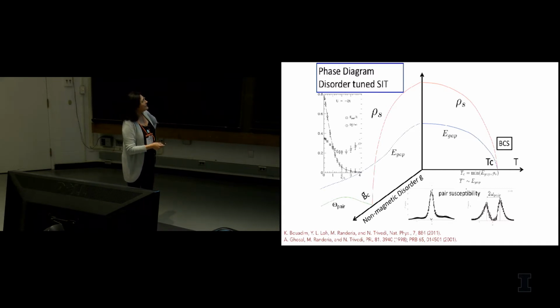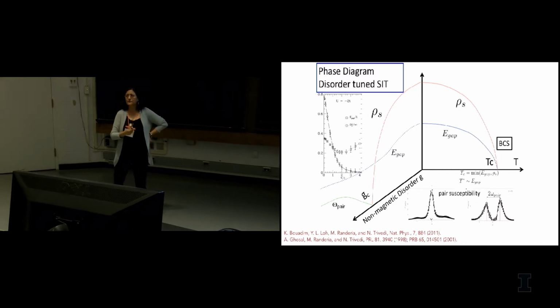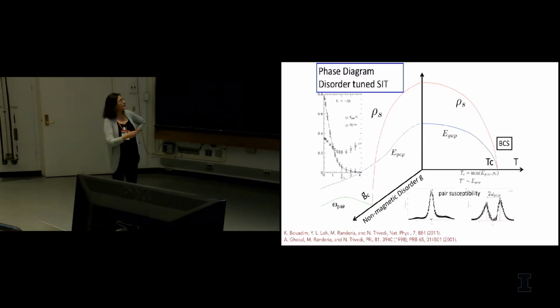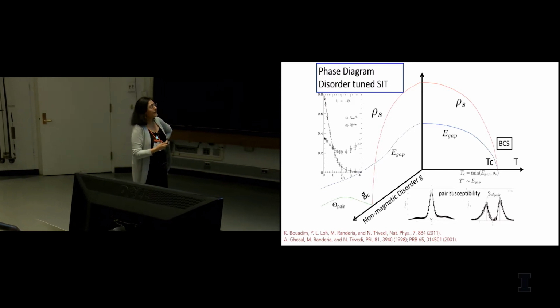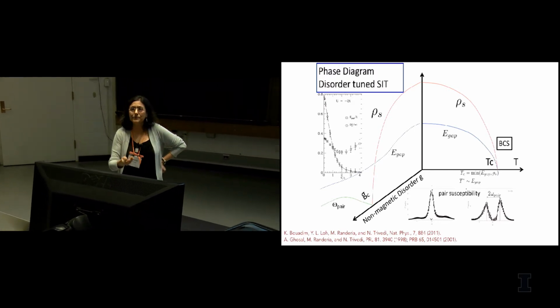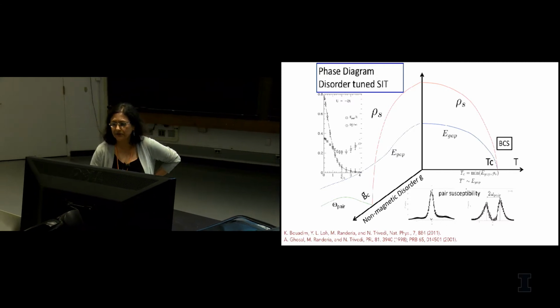And when you enter the insulating phase over here, then this peak at zero energy becomes, it costs some energy now to insert a pair, and that opens up a gap here in the pair tunneling spectrum. So that's the omega pair, which you can see vanishes at the critical point and then grows as you enter the insulator. So this, in a way, captures the phase diagram when you take an S-wave superconductor and add disorder to that.